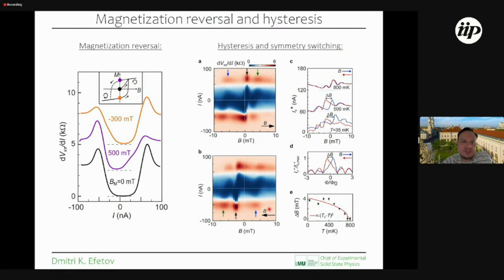And of course, we wanted to quantify this a little bit more. So we have, for example, measured the system when applying a minus 300 millitesla field. As you can see, the junction is tilted to one direction. When we apply a positive magnetic field, the junction is tilted in the other direction. But whenever we warm up the system and cool it back down, the dV/dI characteristics are again completely normal and completely symmetric. So something really magnetizes the system, and before we ever apply a magnetic field for the first time, this magnetization is gone, and it really disappears by warming up and cooling down.